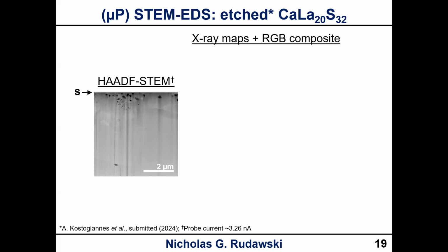So you see an interesting microstructure here where we have some porosity near the surface. We have some granularity. It looks like the grains get bigger. Unfortunately, we have some wonderful curtaining there because of those pores, right? Unfortunately, that's what happens: those pores serve as nucleation sites for curtains when we do FIB, okay? But it's kind of unclear looking at the microstructure how this would relate to the composition, okay?